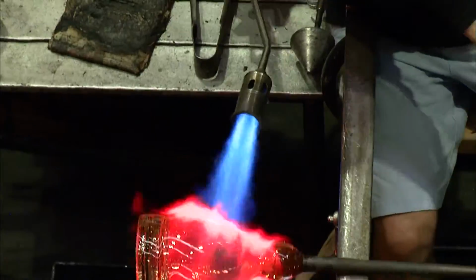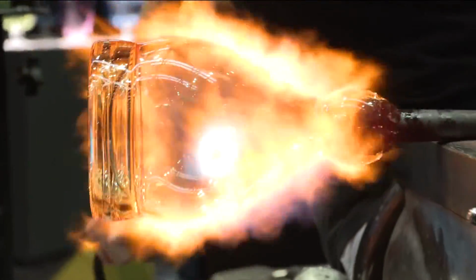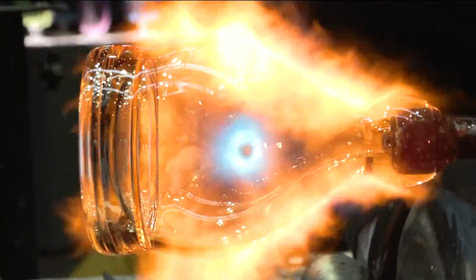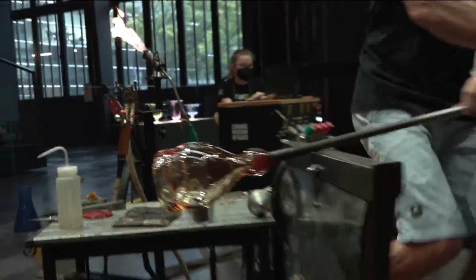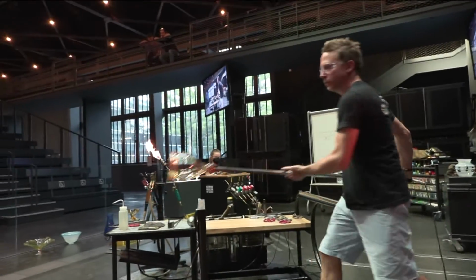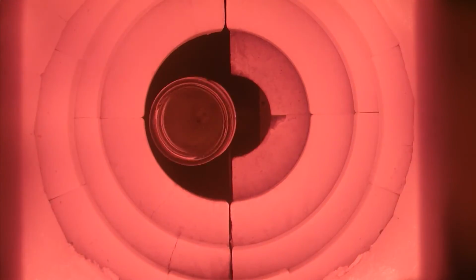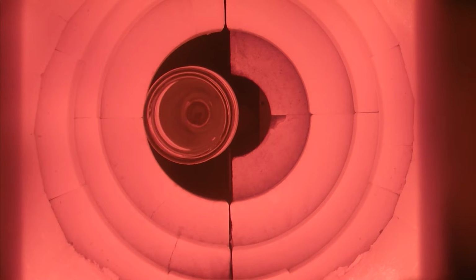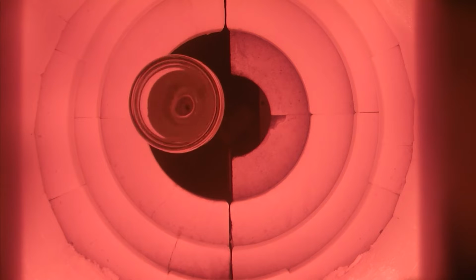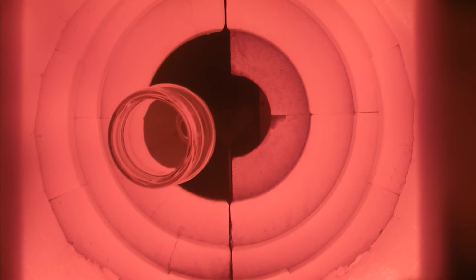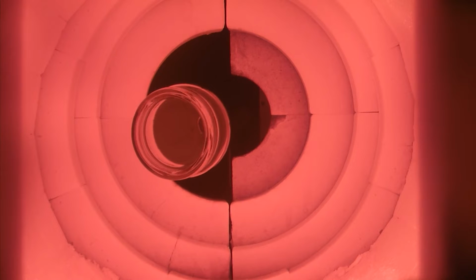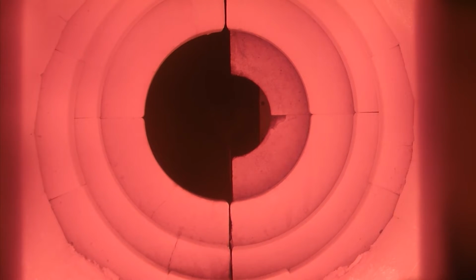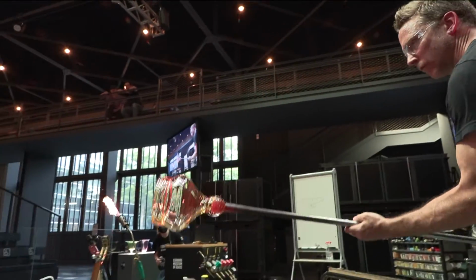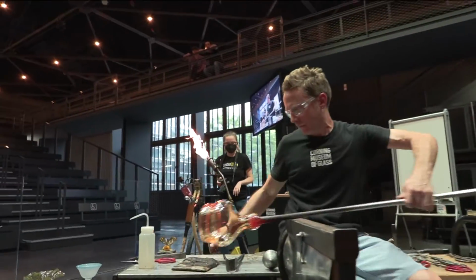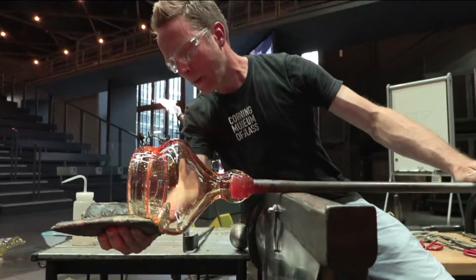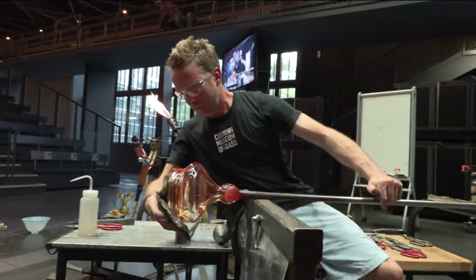The bright orange color that he overlays might not have the same characteristics as the clear glass he's putting it on. And one characteristic that glass has that's very important to glass makers is called the coefficient of expansion. That basically talks about how the glass moves as it cools down and as it heats up and how much it does. And if the coefficient of expansion of one glass is way off from the coefficient of expansion of another glass and you try to put them together, they will break. They have to be within a couple of points of each other to be considered compatible.